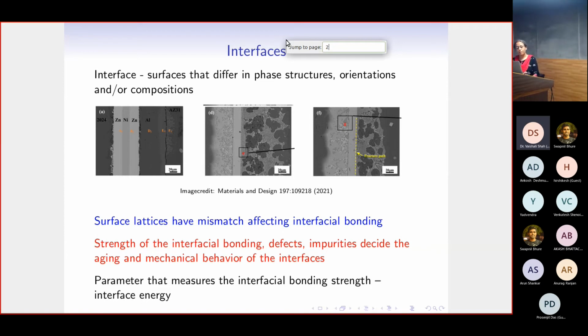The primary reason this happens is because of the lattice mismatch between the different phases of the crystal structures, or because of the different compositions of the crystal structures. Because of this lattice mismatch, there is a difference in what we call the interfacial bonding, which is the primary reason for everything related with the evolution of this interface structure over a period of time, as well as how it will affect the mechanical behavior.